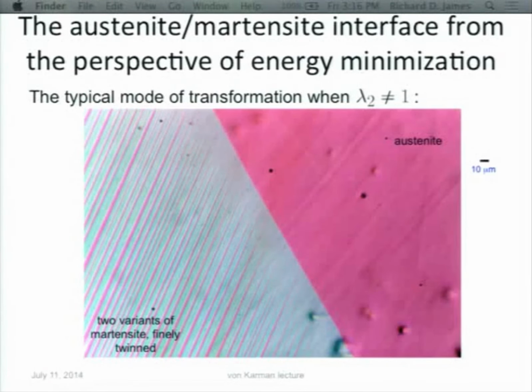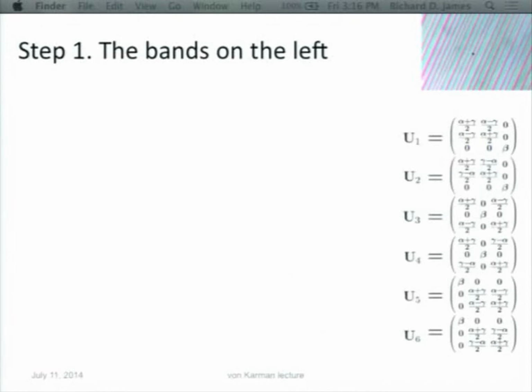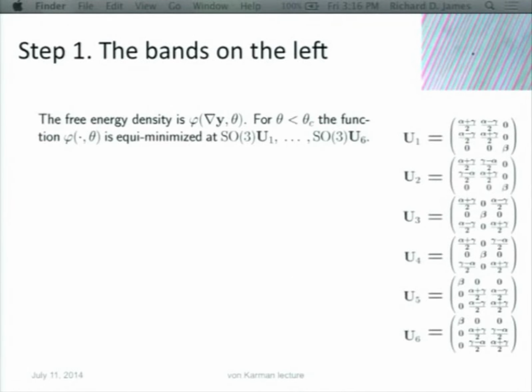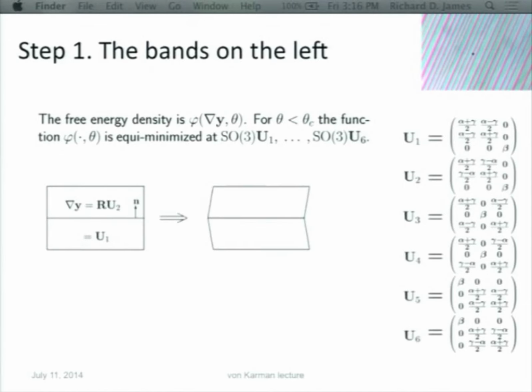That's the cubic austenite phase, and this is in fact 2 of the variants of martensite alternating. So in moving this interface, the unit cubes of the austenite transformed in 2 different ways in the 2 bands. And you can analyze this from the perspective of energy minimization. So I'll do a hand calculation of energy minimization. I'm going to minimize energy by minimizing the integrand, and you can be on one of those energy wells if you put the deformation gradient equal to U1 on one side of an interface and R U2 on the other side of the interface. As I said, U1 and U2 are accurately known.